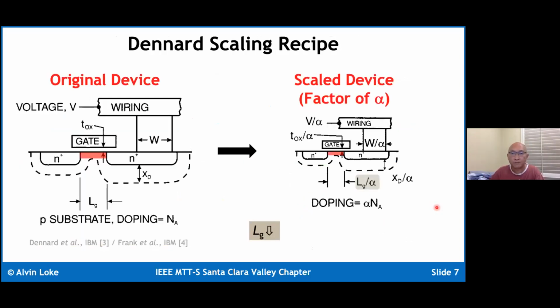Okay, so the blueprint that the industry has followed for about 3 decades has been the Dennard scaling recipe. And so the idea is that when you have a device that's of this size and you want to scale it by some linear dimension alpha, the first thing you do is you want to reduce the gate length, but reducing the gate length comes with it several consequences you have to address. So one thing you obviously need to do to reduce short channel effects is to reduce the thickness of the depletion regions, which requires the doping concentration to go up.